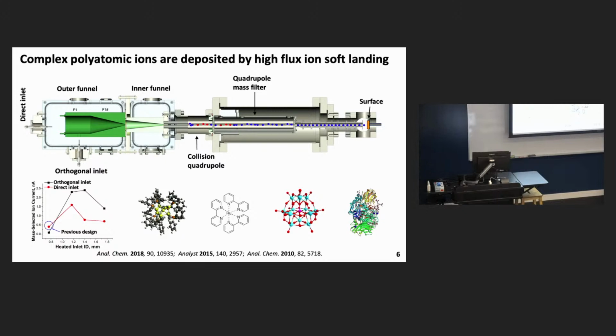Our approach to preparing these materials on interfaces involves ion soft landing using the instrument shown schematically here. We typically start with species in solution. We introduce those to the gas phase using electrospray ionization. And then these are transmitted into vacuum through an inlet, which removes the solvent and converts a droplet basically into a bare gas phase ion. We have two high throughput electrodynamic ion funnels which transmit those desolvated ions into vacuum. And then we have a quadrupole mass filter which we use to pick out one species of interest from that broader distribution of ions, which is then deposited onto a surface through a series of lenses.